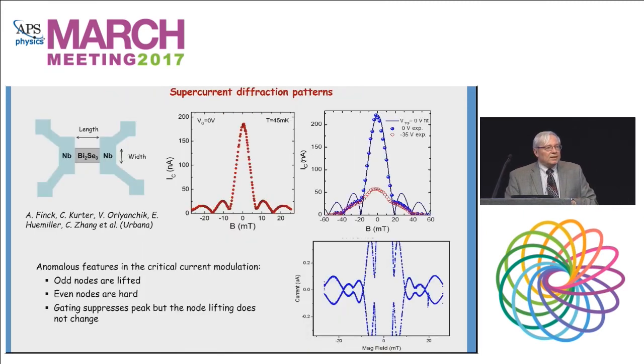So is there any evidence for these Majorana states? Well, we think there is. If you look at junctions of niobium, bismuth selenide, niobium, we see a more or less Fraunhofer diffraction pattern. But note that the first node is distinctively lifted in this pattern.